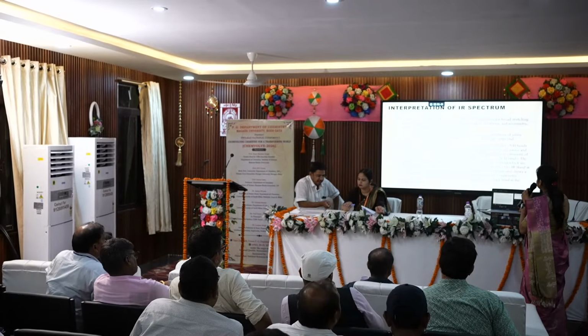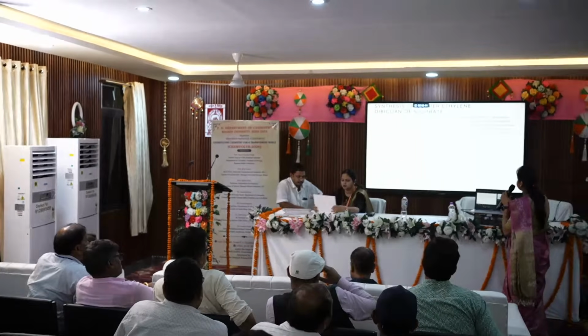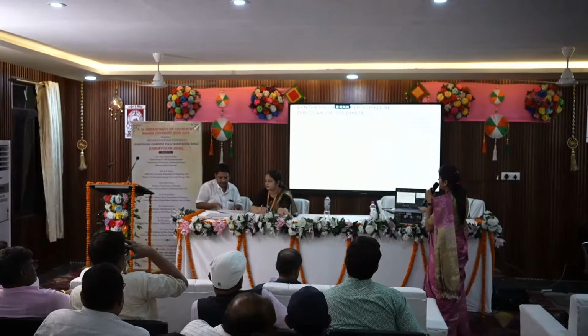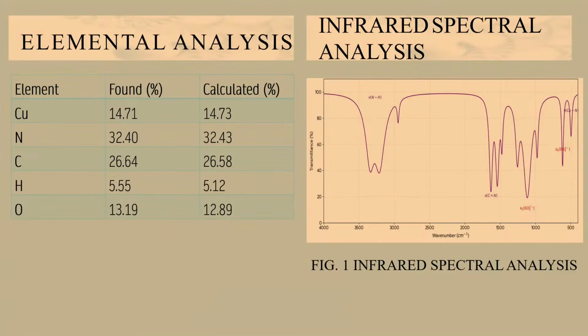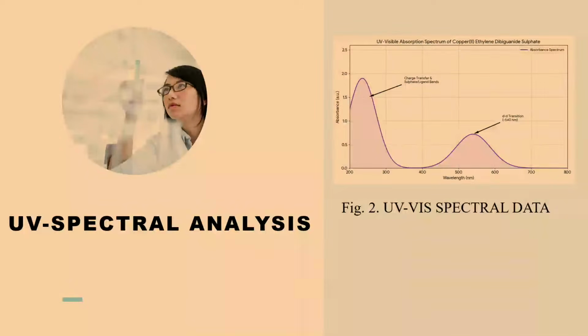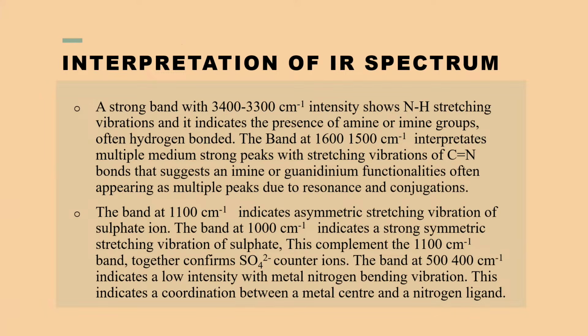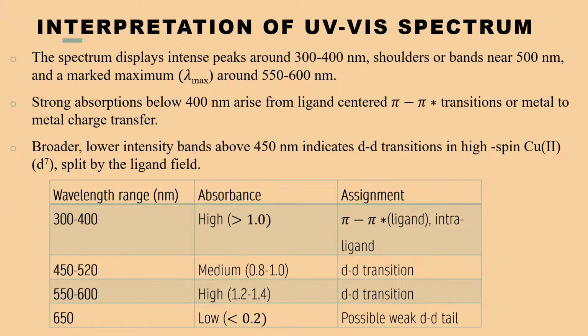This is the interpretation of the UV spectrum and IR spectrum. Then the synthesis of the metal complex, that is copper ethylene dibiguanide sulfate. This is the elemental analysis and the IR spectral data, which shows the peak around 3400 is the NH stretch, while the peak around 1500 shows the CN stretch. The peak around 1100 shows the sulfate stretch, and the peak below 500 shows the copper-nitrogen stretch, which corresponds to the metal complex. This is the UV spectral data. The broad peak below 300 shows the charge transfer spectra, while the peak around 500 to 600 shows the d-d transition. This is the interpretation of the IR and UV spectrum.